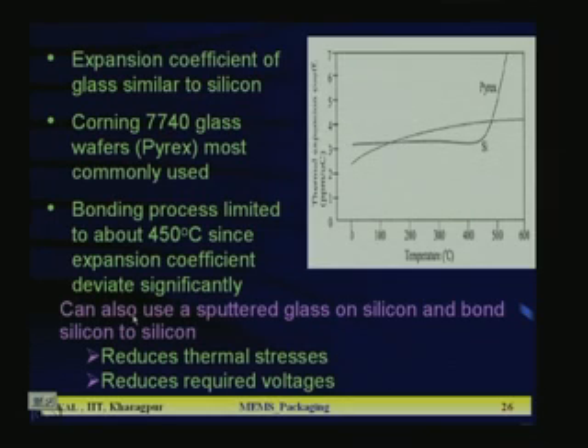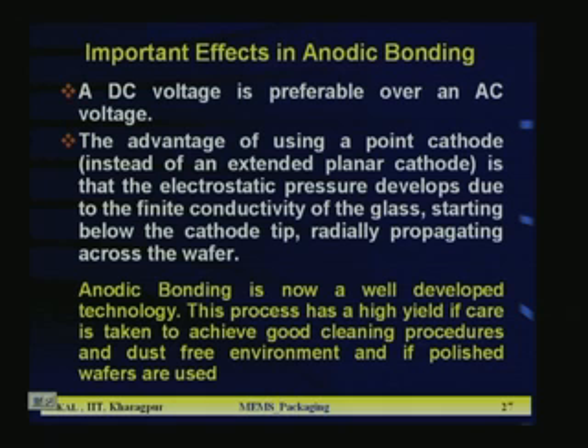So, one can use a sputtered glass on silicon and bond silicon to silicon. If you need silicon to silicon bonding, it requires a glass, because the glass sodium ions should migrate. So, what you should do, a thin layer of glass is sputtered on the silicon, then you go for silicon to silicon bonding. So, it reduces the thermal stresses and it reduces the required voltages also.